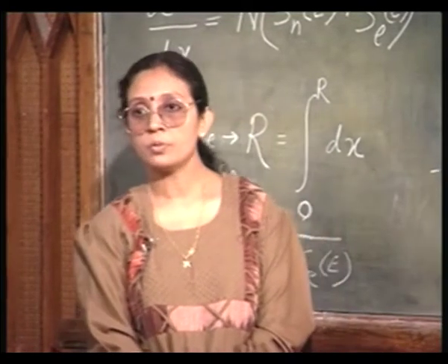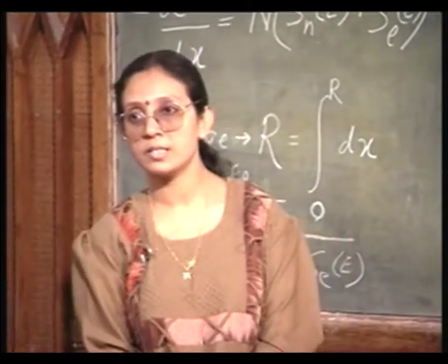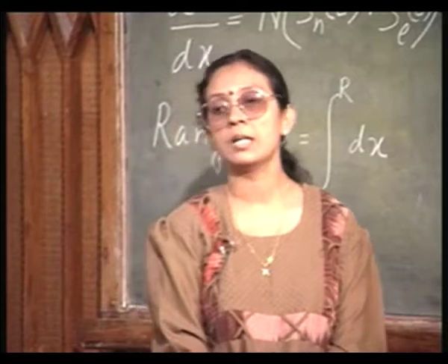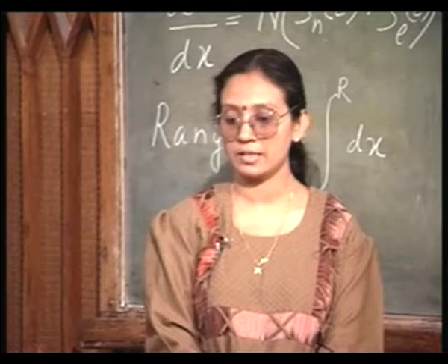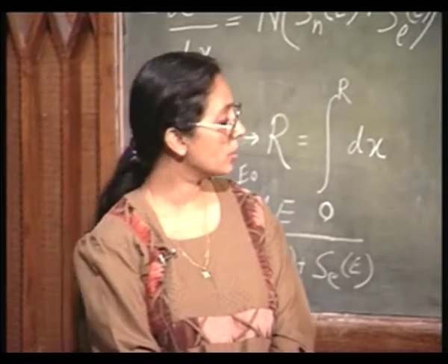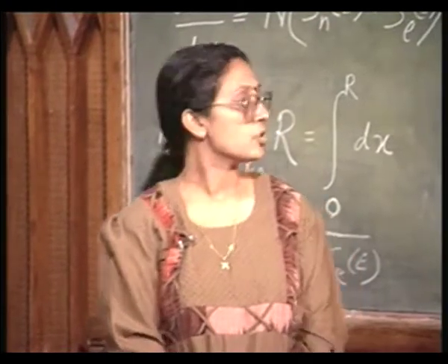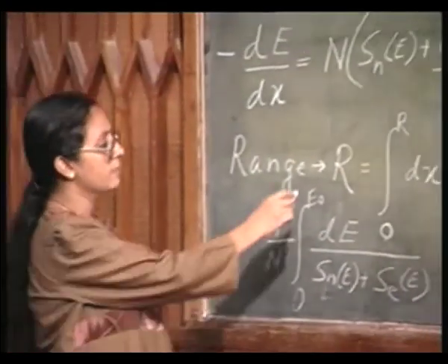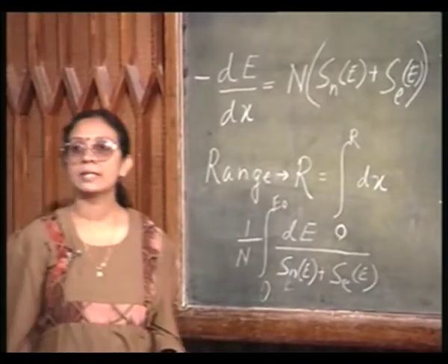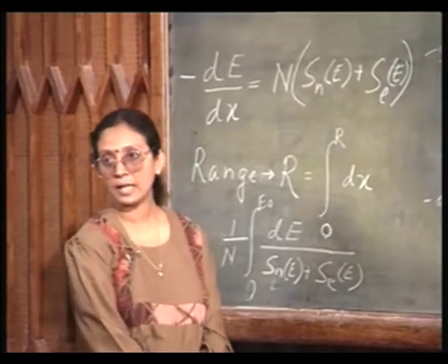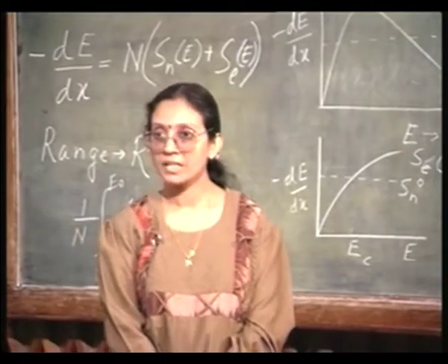Okay. So, I am going to define two zones, two regions of ion energy. When the ion energy is very high, electronic stopping is going to dominate, that is there the ion energy is much greater than the critical energy, and below critical energy the nuclear stopping is going to dominate. So, now accordingly let us come back to the range R, and accordingly therefore, I can take one term and neglect the other so as to give me a relation for the range.